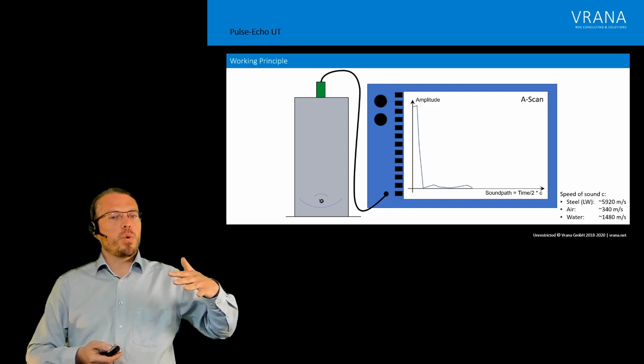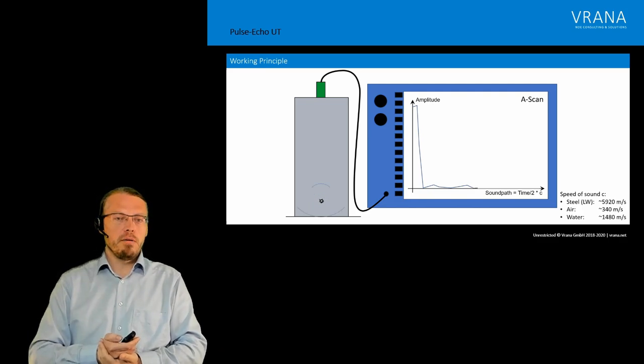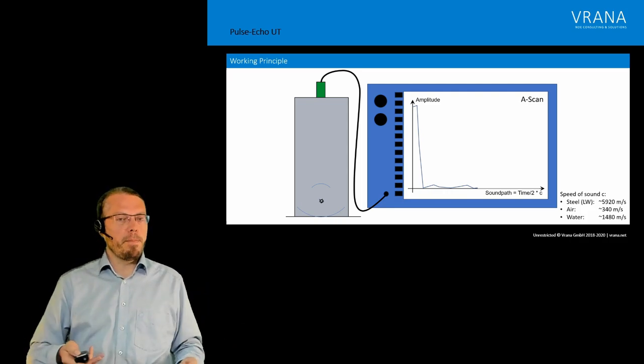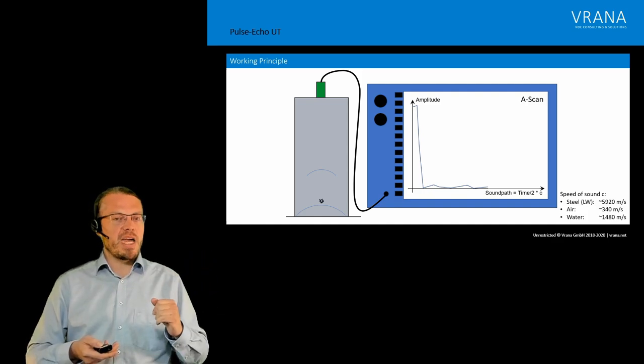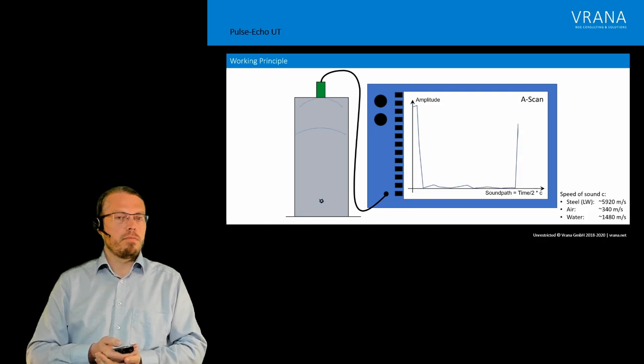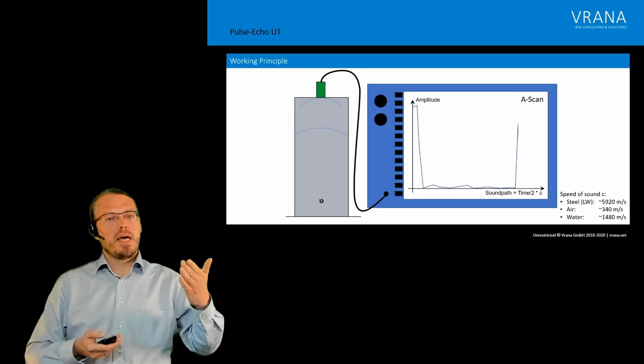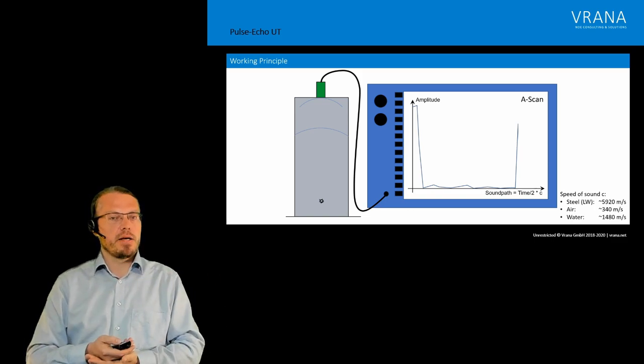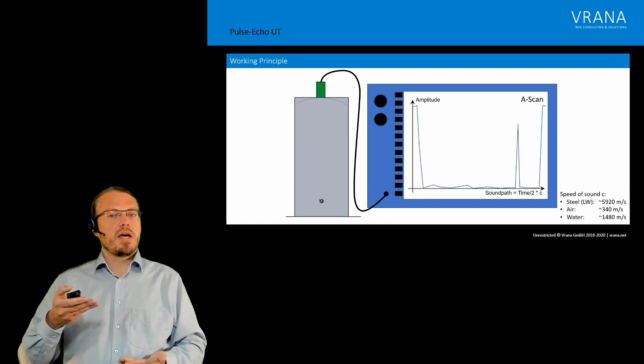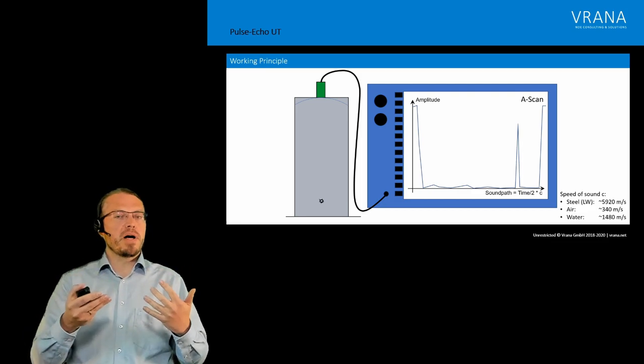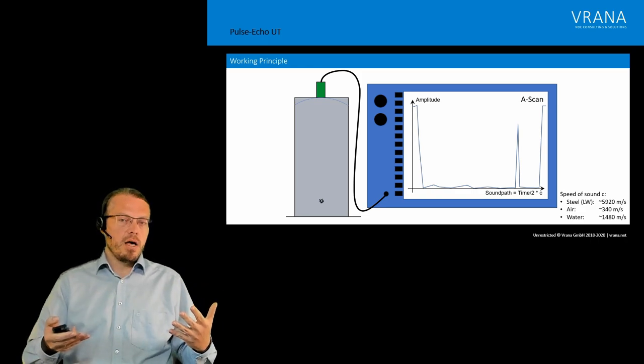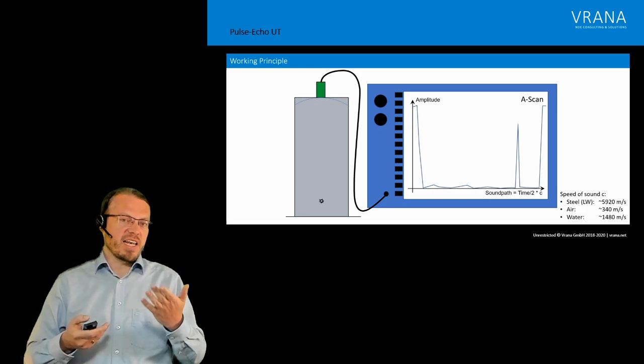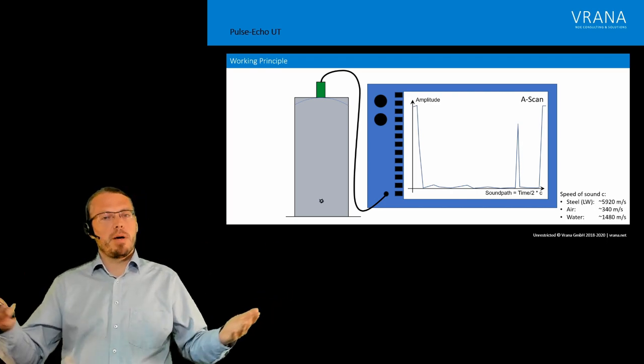But it also has to travel back from the indication back to the surface so that we can see it. All what we have seen up to the moment of the A-scan is actually the dead zone in the beginning and then some noise from the first half of our component. Now we are getting into a wave which is reflected back from our defect but another one which is traveling further to the back wall. Now we are hitting the back wall and that wave gets reflected also on our back wall. So now we have two waves coming back, one from our indication and one from the back wall. Now our first wave actually hits our probe and now we are seeing the signal on our A-scan. And a couple of hundred microseconds later we also see a signal from the back wall. This is a typical screen you see on a pulse echo A-scan. You can see something like that. That's typical signal of an indication. You see the dead zone and you see a back wall.